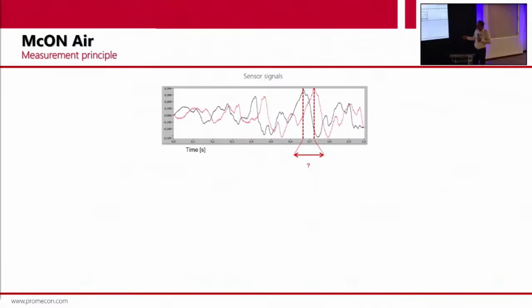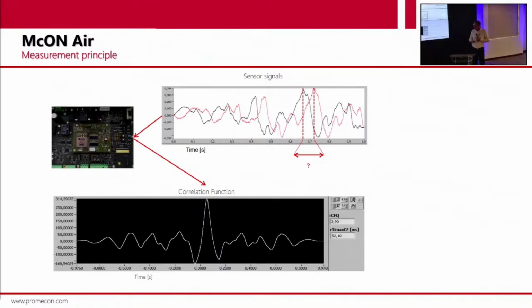So if you put those two signals into a cross-correlation filter, you will get a cross-correlation function. What is that function? This correlation function measures the overlap of the sensors. How much is the overlap? You can see here the overlap is not very big. But if you shift the two functions, you will get to a point where the overlap has a maximum, right? And that means at a certain point in time, we know the time of flight from one sensor to the other. We're just clocking it out. And by this measurement, the dust, which is usually the natural enemy of flow measurement, becomes our tracer. We trace the gas velocity by the dust.